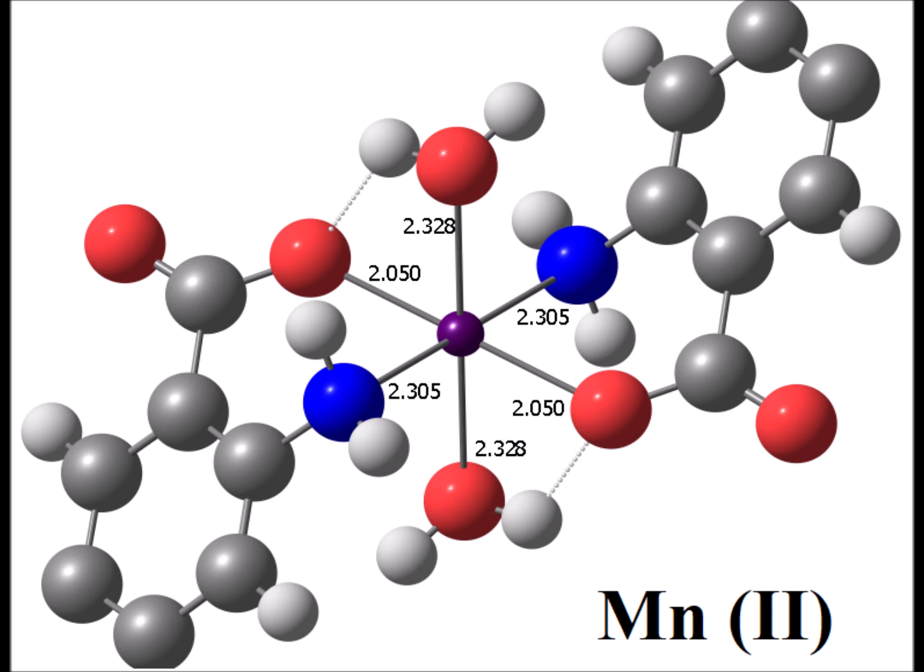Now, to determine the actual electronic magnetic environment, what we do is we measure the samples in both a magnetic field and outside of the magnetic field by seeing the difference in forces involved, that's going to be proportional to the number of unpaired electrons. And then we can calculate. In the case of manganese two plus, it turns out that is experimentally a high-spin octahedral conformation.